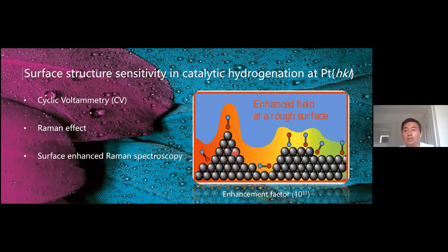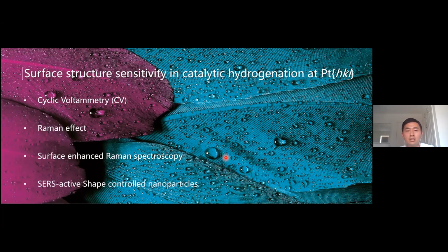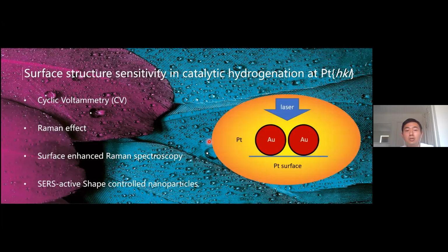The key is that the surface needs to be rough, and only gold, silver, and copper are surface active. So a kind of surface active, shape-controlled nanoparticle was designed to allow us to see the molecules adsorbed on platinum, which was not surface active, but by borrowing the long range effect of the surface active gold core, we could see the vibrational modes of molecules adsorbed on platinum.